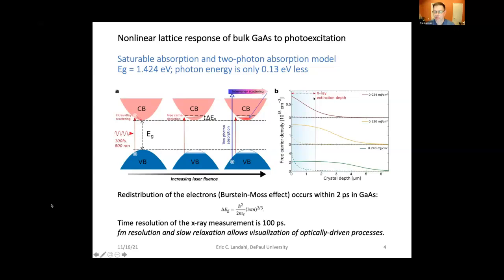So to look at those first two panels here, here's a linear absorption due to single photon absorption. This is the profile against the crystal depth in microns and the carrier density ranging up to 10 to the 18 or so per cubic centimeter. That's initially created at the low fluence. As it's increased, the material becomes increasingly transparent due to the free carrier depletion, and the laser light simply penetrates longer.